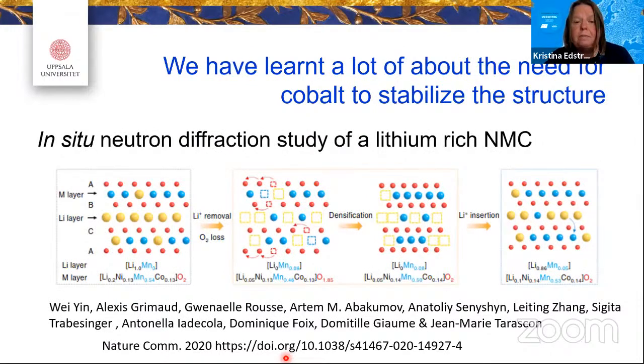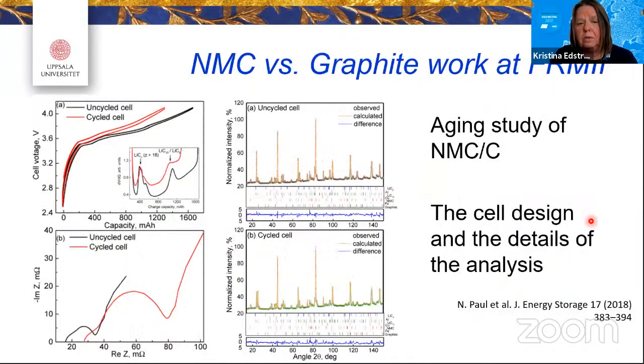So I think we have learned a lot from neutron techniques, and I just want to highlight this example from my colleagues in the Battery 2030 Plus Consortium, also working together with Anatoliy Senyshyn at FRM2, where they really have used in situ neutron to be able to follow the mechanism, which can become quite complex in some of these nickel, cobalt, manganese oxide materials. There can be loss of oxygen and formation of different defects in the structure, etc. When you have these materials, you can look at densification of the materials to change this, etc. And so these reactions during delithiation and lithium insertion of the material are extremely important to know a lot about. And then you often have to compare it with other methods too. But I would say that there is a unique selling point for neutrons in this.